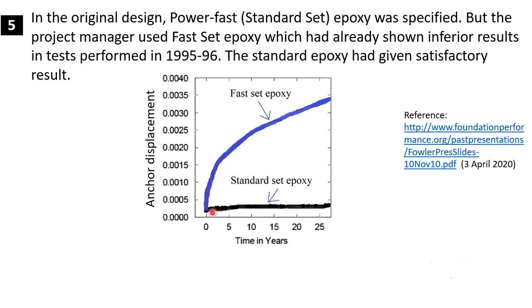And the test showed that standard set epoxy had very little movement for more than 25 years, whereas fast set epoxy had very large movement or displacement of the anchor. So that means this epoxy was inferior in quality,